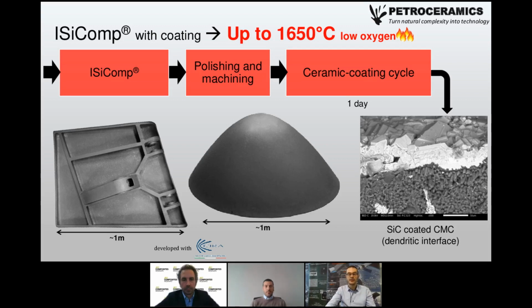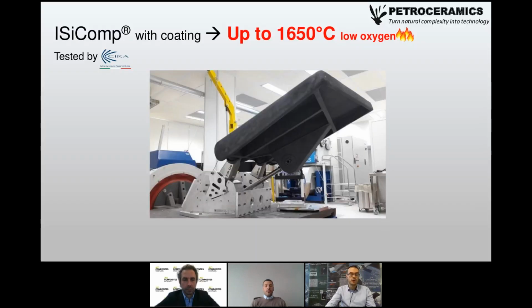You can see on the right the SEM image that shows the amazing interface between the composite and its coating. For this reason, silicon carbide coated ISiComp was selected by CIRA to manufacture some components of the thermal shield of the reusable Space Rider vehicle by the ESA. And in these pictures, you can see the flap and the nose of the vehicle. The mechanical resistance of the coated ISiComp was also tested through a simulation of real mechanical stresses, which the flap will undergo during the launch of the vehicle. And tests were performed by CIRA in their facility.